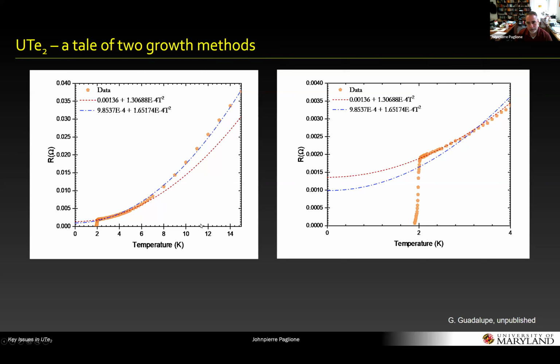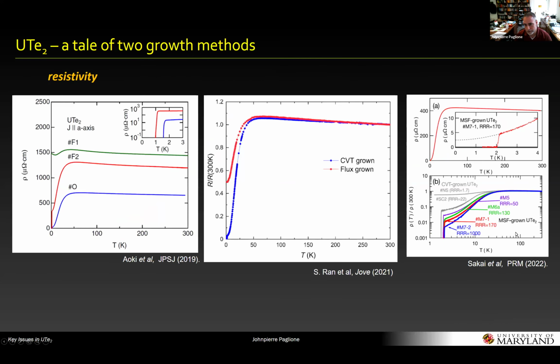For example, you have to be a bit careful when you compare the so-called RRR value of crystals. Just a word of warning. So, sorry if I go back one. There's lots of RRRs compared here, for instance, from 50 to 1000 in the Sakai paper that reported the salt flux crystals. You have to ask how do you define this RRR, because a factor of 2 means a big deal if you're talking about 500 or 1000. And so you have to be careful about how this is actually analyzed.